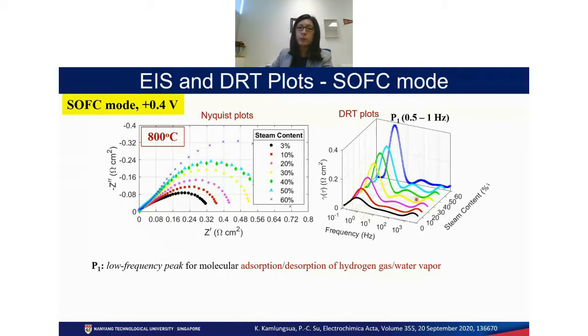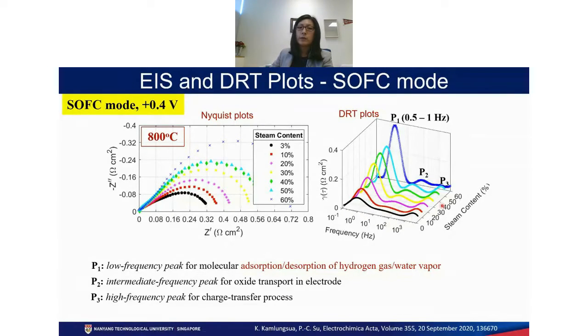There are another 2 peaks: the intermediate frequency peak for oxide transport within the electrode, and the high frequency peak for the charge transfer process. Again, we look at this low frequency surface reaction peak, and we can see that it's increasing, meaning that the increase in impedance is from these surface reactions. Why is it increasing? This can be explained because this is under SOFC mode, and the hydrogen and the vapor coexist. When we increase the water vapor contents, the hydrogen is being diluted, and that causes this increase in the polarization resistance on the surface of the electrode.